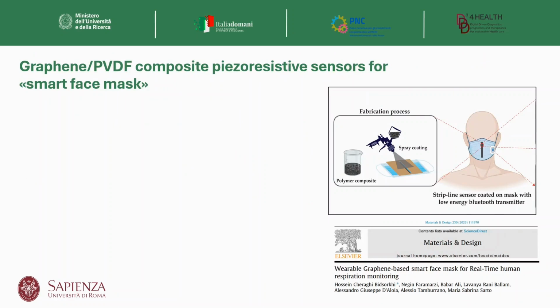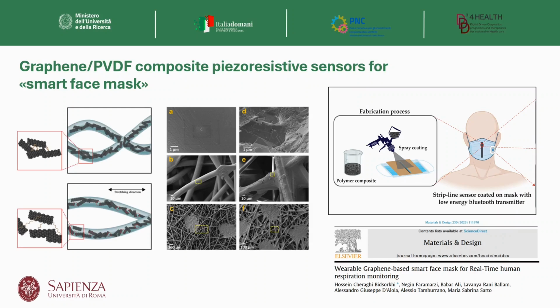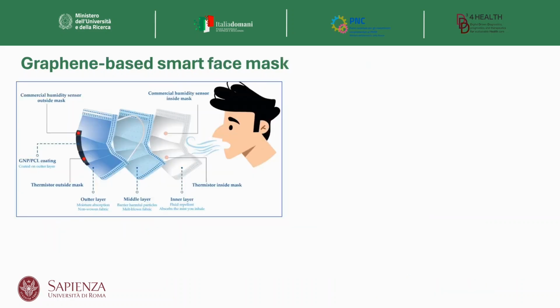I will give you a quick glance at these sensors. The first one we realized in order to make a smart face mask, a face mask that enables us to measure the respiration rate. Actually, we have integrated with a spray approach our polymer that we fabricate integrating graphene inside. So basically the mechanism that produces the piezoresistivity, of course, is the deformation of the polymer that is integrated in the textile of the mask, and therefore it changes the effective resistance.